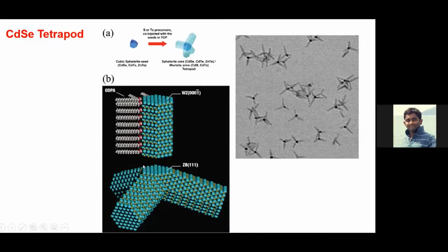So here you can see the structure. These are the head parts inside, with a cubic structure, and from the four faces it grows as a wurtzite phase. So you can see the four legs, and from this you can also get different emissions and different electronic properties. It is interesting because you have two different crystal structures in one system, a zinc blende system and a wurtzite system in a single structure. That's why you will have different electronic and optical properties from that tetrapod.